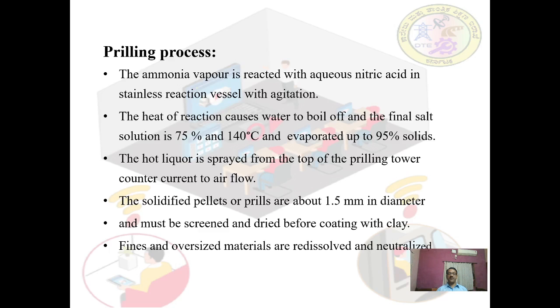In the prilling process, ammonia vapor is reacted with aqueous nitric acid in a stainless steel reaction vessel with proper agitation. Agitation is required for maintaining the uniform concentration of the reactants in the reactor, and also to maintain uniform temperature in the reactor. Because it is an exothermic reaction, the heat of reaction causes water to boil off, and the concentration of ammonium nitrate in the solution increases to 75% at 140 degrees Celsius. This solution can be evaporated to concentrate up to 95% solid content, that is, ammonium nitrate content in that solution.